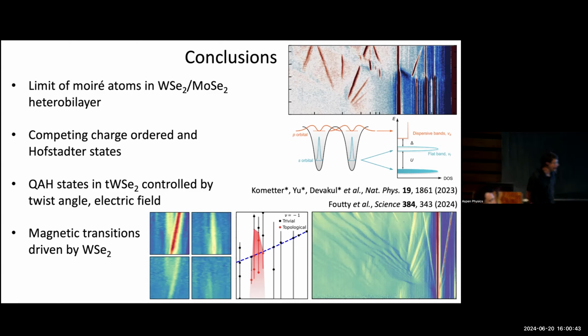So I think one would indeed say that, in order to stabilize the topological phase, there should be some associated entanglement between the carriers. I don't know anything about, for example, the more traditional quantum entanglement. Let's say you have spins on individual sites, are they entangled with one another? My guess is probably not. The reason is that the systems we're looking at here have a very long Moiré wavelength. What that means is that the exchange interaction, for example t squared over U, is very, very small, actually much, much lower than the temperature of our system. So any sort of spin ordering wouldn't happen unless we went to much, much lower temperatures, like a millikelvin or something. And so you should think of these states all in the spin disordered limit or the paramagnetic limit in the zero field case. When you apply a field, you polarize them all.